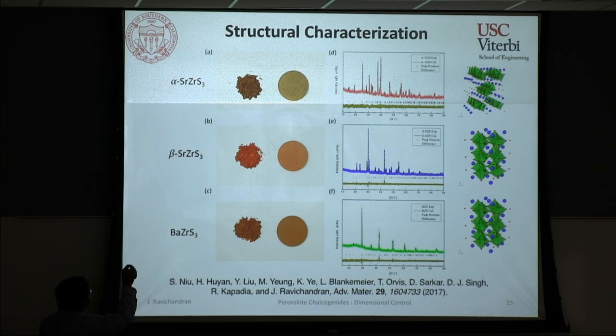We also were able to stabilize the strontium zirconium sulfide, SrZrS3, in the needle-like phase that I showed earlier. And also by heating up this material to high temperature and quenching, we were able to metastabilize the 3-dimensional corner-shared perovskite too. So in some sense, we could even achieve 2 different phases of the same composition by just working with the way we are processing these materials.